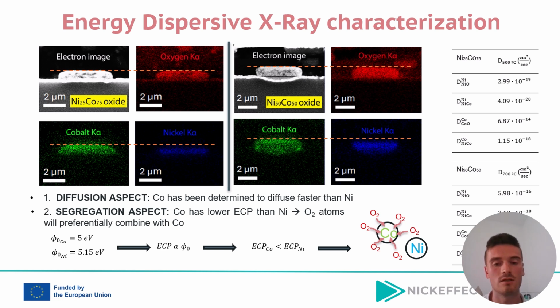Actually, these two findings could theoretically confirm why oxygen preferred bonding with cobalt than with nickel, and hence justify why cobalt went to the topmost part of the discs.